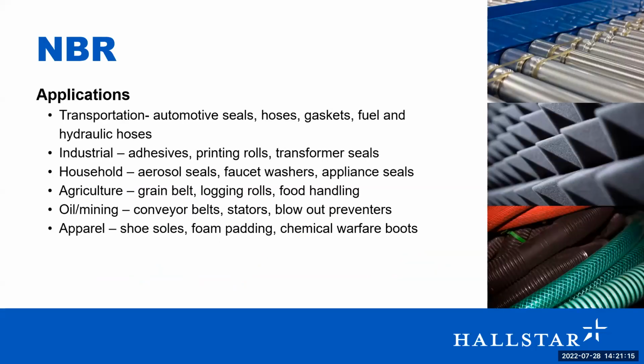So for nitrile, our applications that we're really going to be looking into are going to be applications that are going to have very high oil resistance. So we're seeing hydraulic hoses, adhesive printing rolls, transformer seals. These are aerosol seals, appliance seals, and there are different sort of gaskets and seals a lot of times that need some sort of oil swell. So when we're looking at nitrile rubber, a lot of times people are going to be using monomeric chemistries because they're going to require some sort of volume swell in their nature. So the part usually does require a slight amount of swelling.